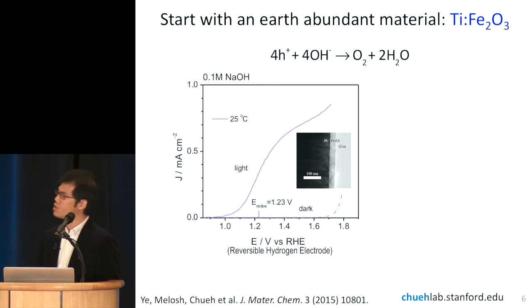So you can see in the dark, you have a quite high onset potential. So the current takes off at very high potential. When you turn on the light, the potential shifts by about 700 millivolt. And this is very nice. So what we want to happen as we turn on the heat to up the temperature, we want the curve to shift further